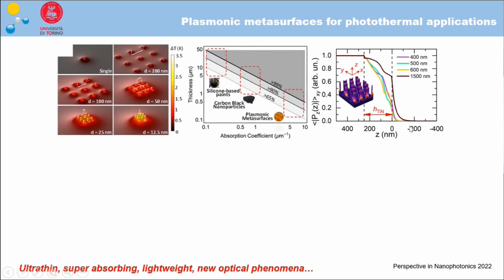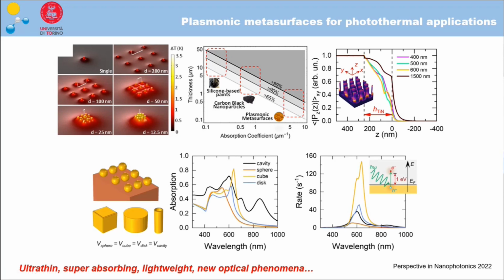Here, from a fundamental point of view, you can see on the right-hand side, for example, a metasurface based on the arrangement of titanium nitride nanocavities or nanocylinders. And you can see that the absorption of light is completed within the first 200 nanometers of thickness. So this, of course, is quite incredible and unique to the properties of plasmonic metasurfaces.